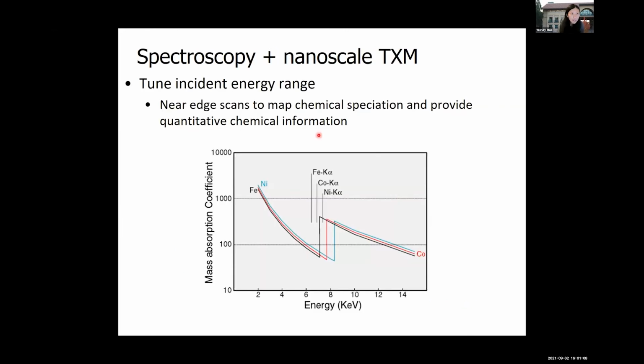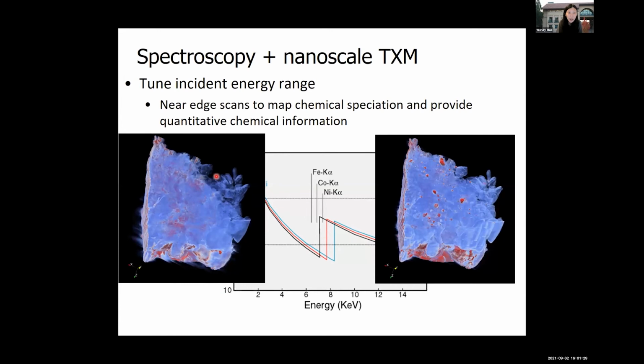Okay, and then very quickly, I wanted to say that you can also do spectroscopy plus TXM. So in this case, because with a synchrotron source, you can tune energy, you can get a dramatic increase in absorption and compare the absorption right below and right above an edge to really enhance elements of interest. So if we look at images below and above the iron edge, then you can see for this sample, that's a mixture of silicate in the blue and red iron alloy, that the iron blobs kind of immediately pop out when we look at the difference between below and above iron edge imaging.